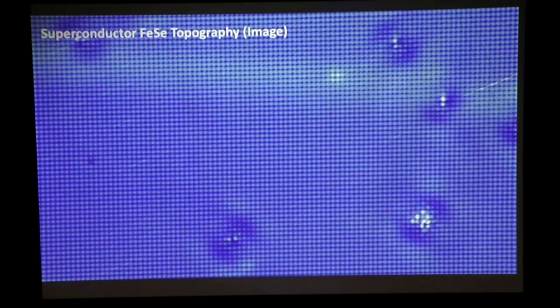So let me give you a few examples of what we can measure. A very popular thing to measure is an image, a topographic image of the surface. This is an image of the superconductor iron selenide. And each of these impurities that you see here, these one, two, three, these are actually single atom impurities. They just look like this because of the density of states. So you've seen hundreds of images like this. It's almost come to the point where you take this for granted. However, there's a huge amount of information hiding in these images.